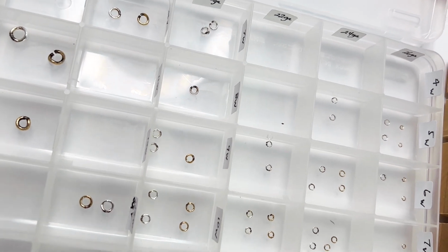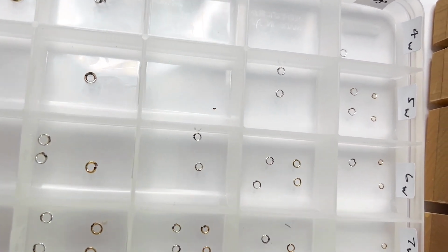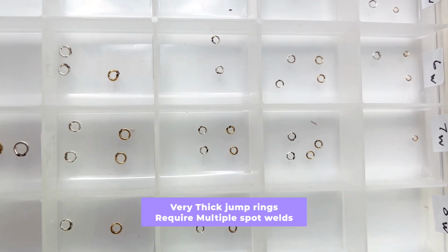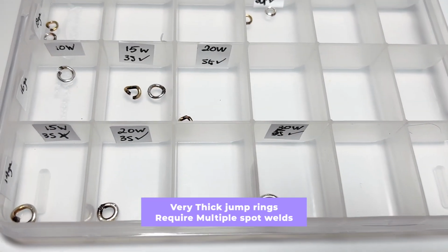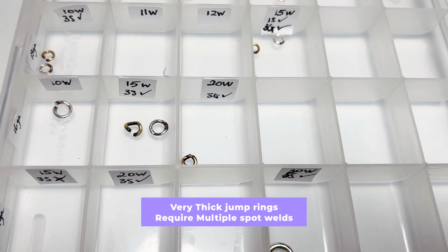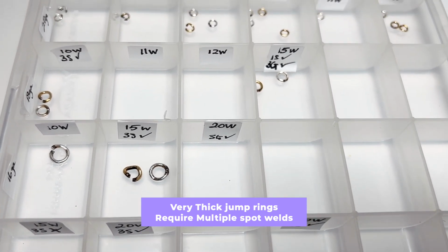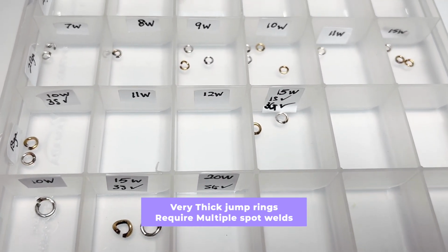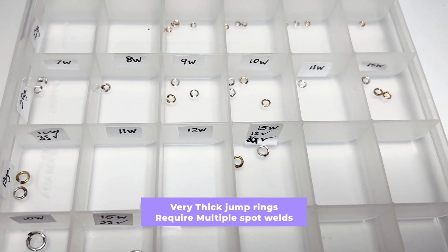When the jump ring becomes too thick though, I notice that I must weld on more than one spot. And in that case, I note the number of welds I must make in order to prevent me from being able to break the weld with force. And that is part of the chart that I'm going to share with you.